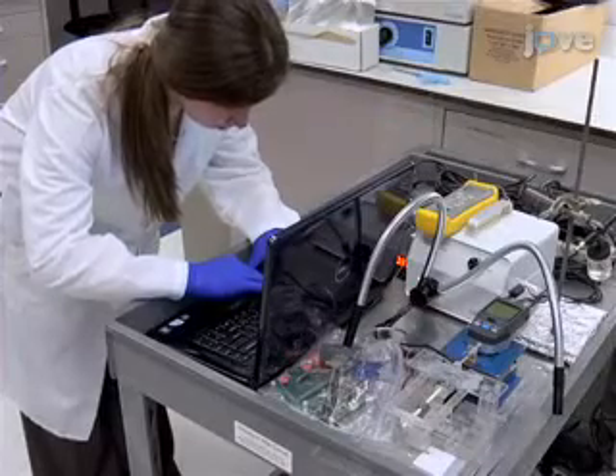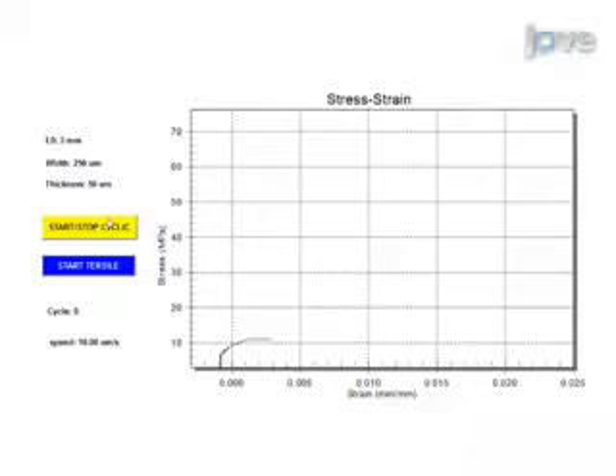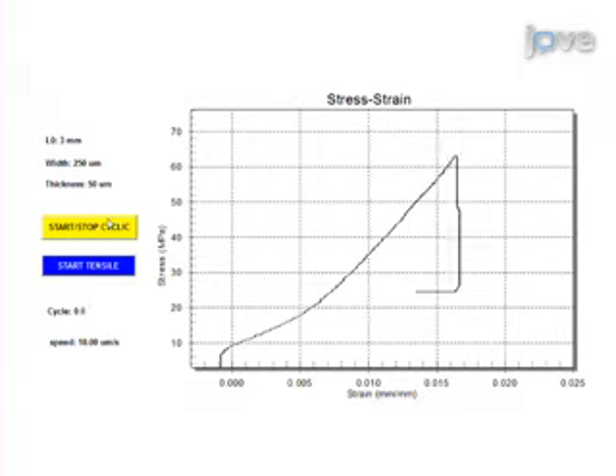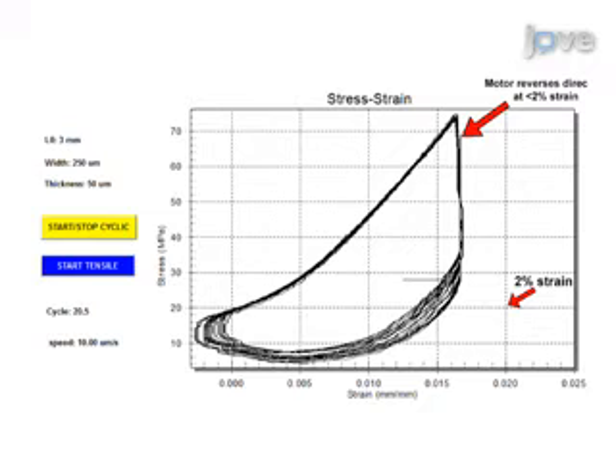Begin the cyclic microtensile testing procedure, alternating between tensile strain and compressive strain being applied to the sample. The test should remain in the linear elastic region of the stress-strain plot. In this case, the applied strain is limited to less than 2%. In these experiments, the strain rate was controlled while the required force to achieve that strain was measured.